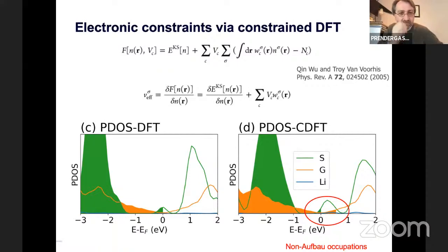We have assumed that the electrons are at equilibrium. And one way to counteract that is to use what's called constrained DFT. So you use your physical intuition to say, well, I know that my electrons should be holed up, localized in some region of the system. And so what I'll do is define a constraint that keeps them there. And then I can do my Kohn-Sham equations with density functional theory, or whichever theory you're using, with this constraint, and it just adds a correction term to the potential.